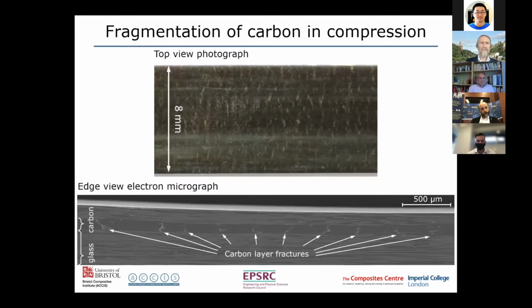So here you see the top view of the specimen, and it has this similar sort of pattern that we saw in tension, a bit more fine, but similar sorts of patterns here indicating that fragmentation has occurred under compression. And if we look at the side, you can see these angled cracks at quite regular repeating intervals in that carbon ply close to the compression surface of the specimen.